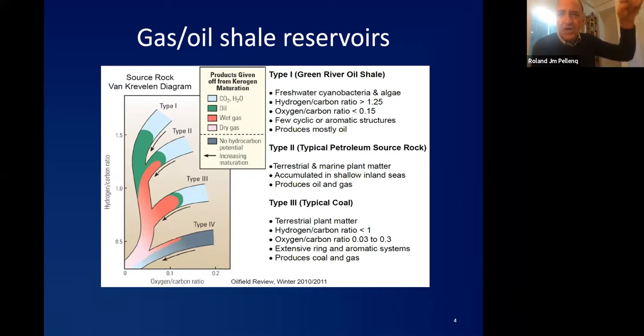And you see, over time those organic molecules get buried, and of course the deeper they get, the temperature is increasing. So there is a cooking of those molecules called pyrolysis. Pyrolysis is a cooking with no oxygen. So basically, we are removing oxygen and nitrogen and sulfur. At the end, we're left with a backbone structure, which is porous. So over time, you go down and to the left. At the end, we have no more hydrogen, no more oxygen. So we have a plateau where at constant hydrogen we are losing oxygen, and then we go down where we have lost our oxygen, and now we start losing hydrogen. Actually, this is the production of those hydrocarbon molecules. So that's typically this kind of thing. There is no time scale there, but from the plateau on the right down to 0, it takes, as I said, hundreds of millions of years, which is a lot.